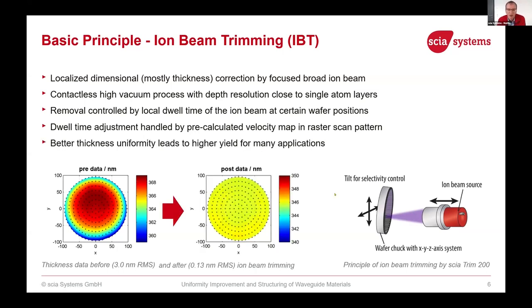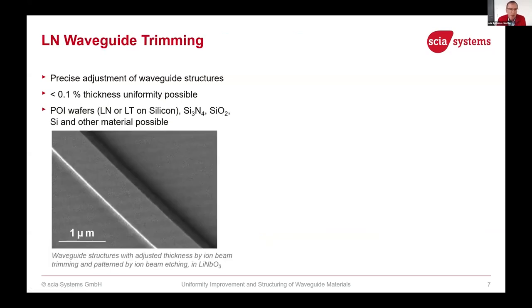Finally, what you want to achieve is a very uniform film thickness distribution or property distribution of your devices, if you already have devices on that. As shown here in the right picture, in this example we improved the variation from 3 nanometer RMS down to 0.13 nanometer RMS by this ion beam trimming technology. This is one nice example. This can also be applied to waveguides, for instance, for lithium niobate waveguide trimming. Here you do this trimming before you structure the waveguide, so just the bare film material is trimmed to a certain uniformity.